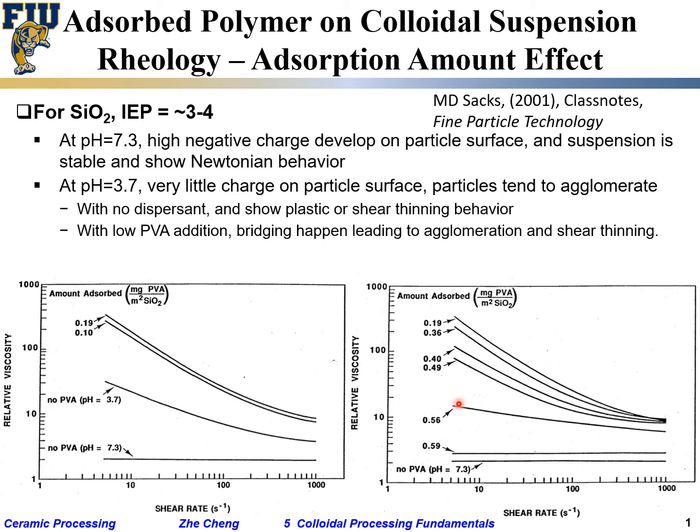When I have a higher polymer coverage on the particles, when I have polymer covering pretty much everything, then when two particles come together, when they get too close, you have to compress. You have to force the polymer to pack dense, which the polymer does not like. When you try to force the polymer to pack dense, lined up like this, the polymers don't really want it. That's what gives it the so-called steric stabilization. The viscosity drops again. It's behaving more like a Newtonian fluid